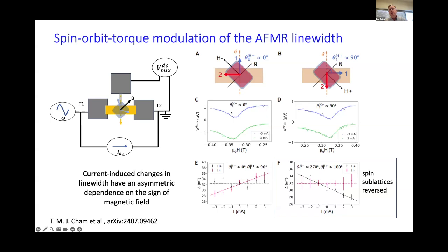And what we see is an effect that's asymmetric in the direction of magnetic field, in the sense that for one direction of magnetic field, we see a strong dependence of the line width on current, indicating that the spin orbit torque is modifying the line width of the resonance. For the reverse magnetic field, there's essentially no effect. And we can explain this as to whether or not the spin sublattice adjacent to the bottom channel is parallel or perpendicular to the spin generated by the spin orbit torque.